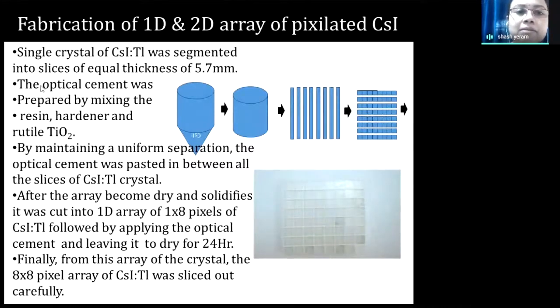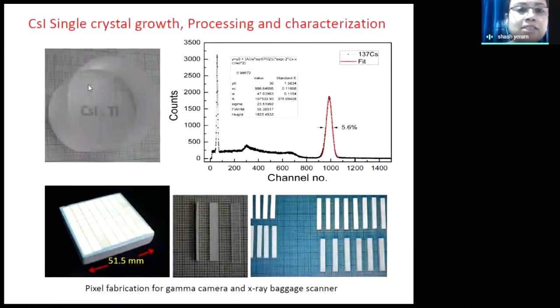So the single crystal was segmented, then optical cement was made using a TiO2 resin and hardeners, and pasted on all slices of the cesium iodide crystal. In this way we have made a 1 by 8 pixel array of cesium iodide, and then 8 by 8 pixel. So you can see, this was the crystal initially. Then it was cut into cylindrical pieces, and now you can see this is a one-dimensional matrix and this is a 2D matrix, meaning here 8 by 8 cesium iodide pixels are there.